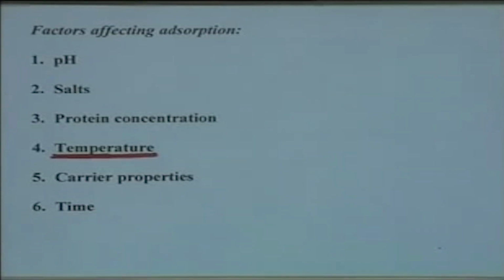But in the case of protein adsorption, when we are talking about enzyme, a macromolecule, adsorption over a narrow range of temperature offers a reverse phenomenon. That means adsorption increases with temperature. Again mind the words, I am saying over a narrow range of temperature increase. If you increase to a higher level, of course desorption also might start, but before desorption even inactivation might start.